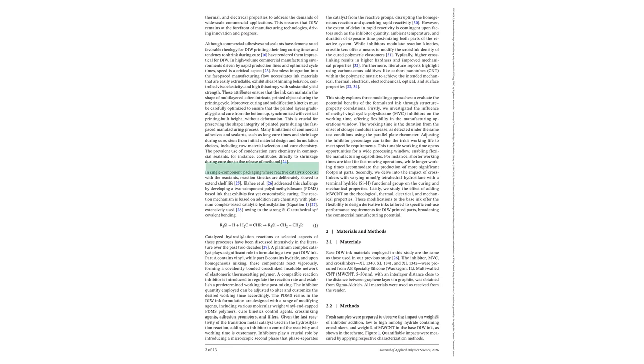The result is a covalently cross-linked three-dimensional network, a solid elastomeric material. Crucially, this reaction generates no byproducts, which means there is no shrinkage during the cure, a major advantage over traditional condensation cure sealants that release molecules like methanol. This formulated ink is designed to gel rapidly at room temperature and then continue to cure as the object is printed, locking in the structure's shape and integrity.